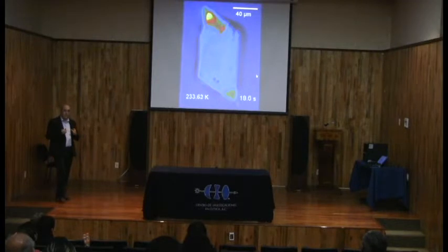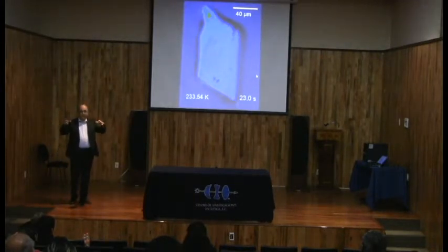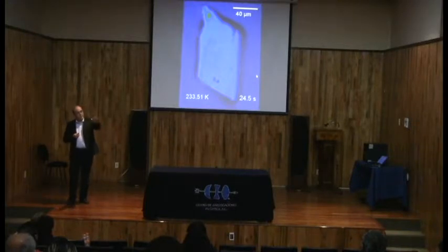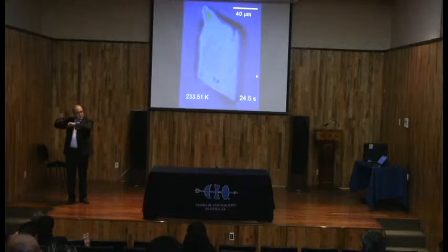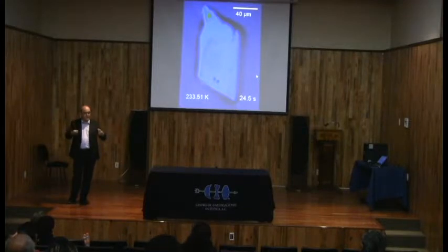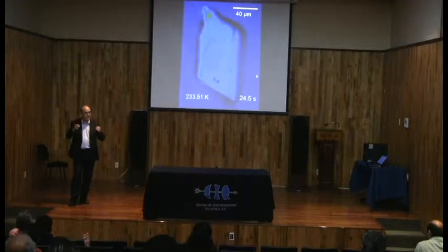Okay? That means that you have your crystal. At the beginning, you have the nucleation, the propagation of the spin state in one direction. You put a defect here, and then the propagation changes its direction. So then it's propagating in the other direction. That means that artificially, if you generate defects in your crystals, you expect to control the nucleation and growth process.